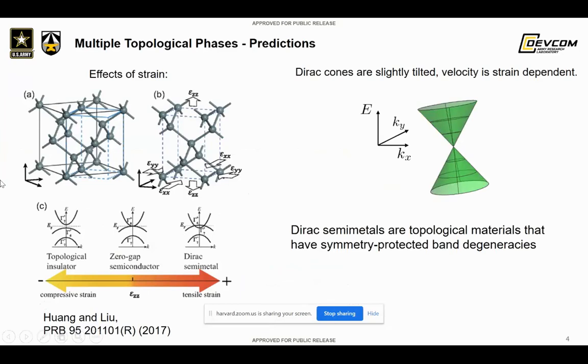The band gap picture shows that under compressive strain, you open up a band gap, but under tensile strain, you can actually have a band crossing, and you can have degenerate crossings at 2 points along the z-axis, which makes it a Dirac semi-metal. So it is possible to achieve topological phase changes if you can vary the strain in the material, or by using lattice strain from the substrate to go from compressive to tensile strain. The Dirac semi-metals are topological materials that have symmetry protected band degeneracies, so they're certainly an interesting topological material.